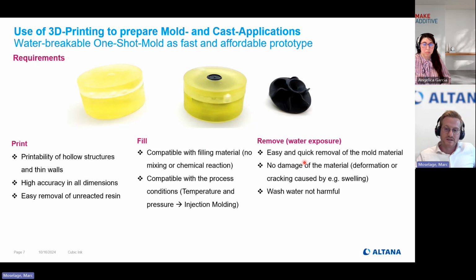Finally, coming to the removal process, what is important there? The removal needs to be easy, quick and user-friendly, also in order to give real benefit to the end user. And the material doesn't need to be damaged. You can ruin your whole process in the end if you have, for example, a deformation or a cracking, which is caused by a swelling of the mold material. So the mold material can fade away, but it's not allowed to swell to a certain point, in order not to destroy the final product. And the wash water you have in the end shouldn't be harmful and should be disposed of quite easily, so as not to cause more problems.